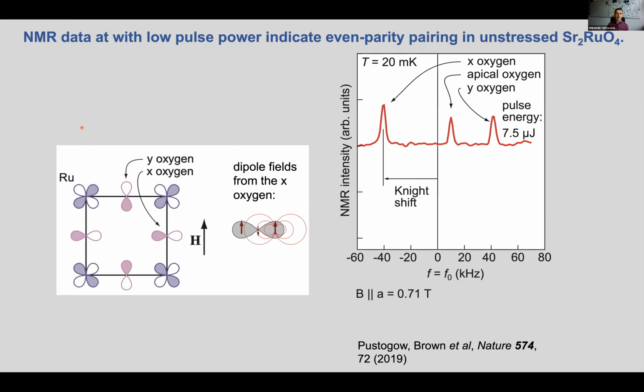And then there's been recent NMR evidence on unstressed strontium ruthenate that the order parameter is also even parity. So here we have the NMR intensity as a function of frequency. Here we have our parallel oxygen site, and here our perpendicular oxygen site.